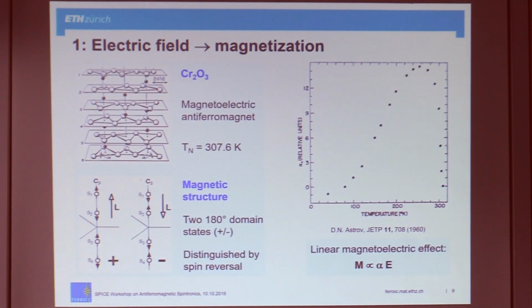And indeed, the first compound where magnetoelectric coupling effects were discovered, an electric field inducing a magnetization, was an antiferromagnet, chromium oxide, about which we have already heard a bit. So chromium oxide has a very simple structure. It's just an octahedral oxygen cage. It's a distorted octahedron. And in 2 out of 3 of these octahedrons, you find a chromium 3 plus ion. The spins of these are up, down, or in the other domain state, down, up. So that's an antiferromagnet. And it allows magnetoelectric coupling effects of the linear type. So an electric field induces a proportional magnetization. And that was found in 1960 after it had been theoretically predicted by Dzyaloshinskii. I think it was in 1958 or 57.